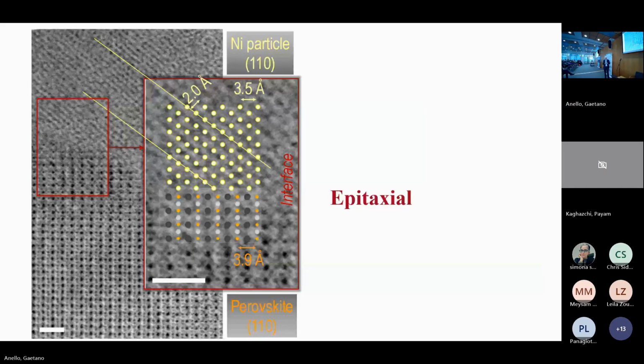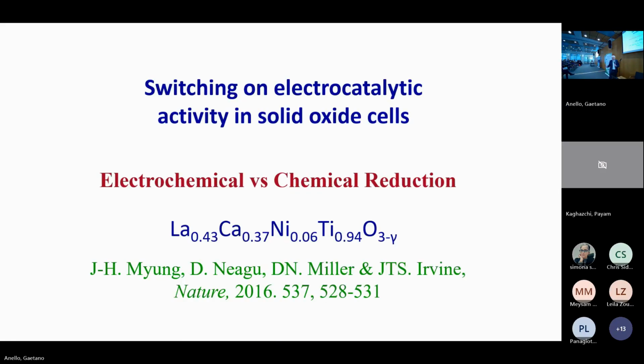And then something that's quite weird is the unit cell parameter. The exsolved particles got similar lattice, the cubic lattice to the perovskite, but the unit cell is 10% different. You wouldn't expect epitaxial exsolution or epitaxial layer interfaces. That's such a big difference in unit cells. So that's really surprising, but you can see that the lattices are consistent. They go across. And so there's a lot of chemical and physical strain there, which is again probably why it's so stable.